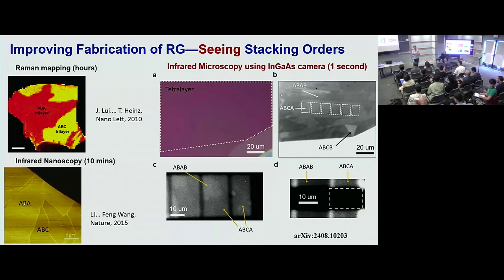Okay. And about the aligned samples, am I correct to assume from your data that at nu equals 1, increasing the D field, the displacement field, you get metal, Chern 0, Chern 1, and then metal, and the Chern 0 state also increases in D region upon cooling down? I'm just asking the sequence. Nu equals 1 as a function of D. Is it metal, Chern equals 0? I see a highly resistive state there. Chern equals 0, Chern equals 1, metal. That's right. And the Chern equals 0 region increases upon cooling down also. Oh, I didn't pay attention to that, but we can take a look later.